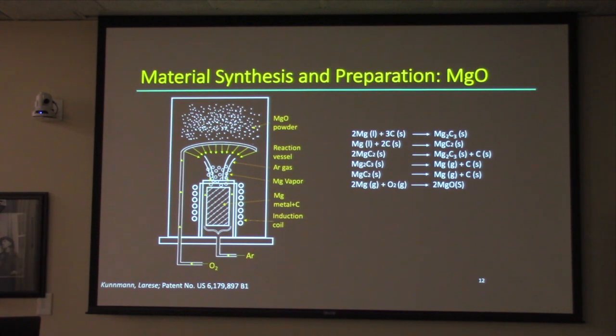We almost burnt down the chemistry department when we first did this because we were oxidizing liquid magnesium in a crucible and then vapor and entraining it. Magnesia crucibles don't handle things very well, and so we finally came along to the fact that we could use graphite particles, form an intermediate carbide, and then decompose it, where we could control not only the fact there was only magnesium vapor in the reactant flow, but also the size of the droplet. And monitoring the size of the droplet determined what the sizes of the particles would become.